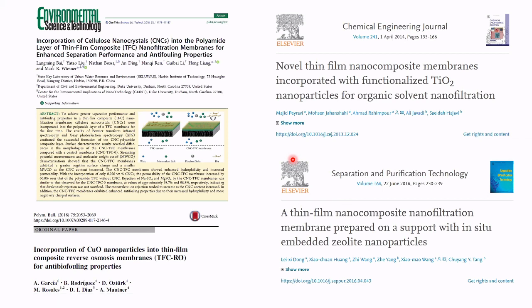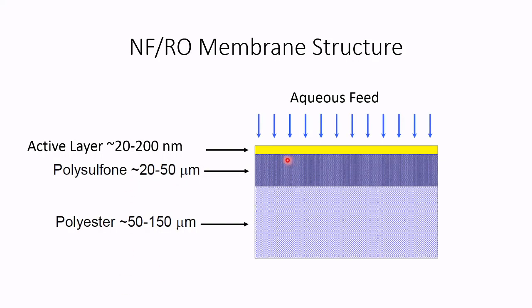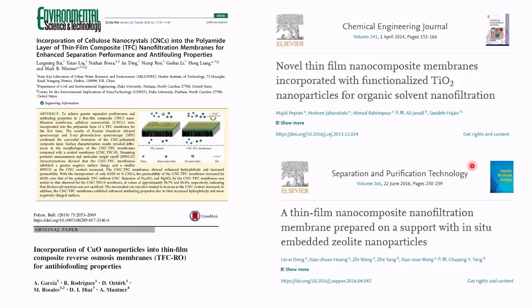So here we see, just to recall the structure of a membrane, the active layer is that top layer. So what these papers are really doing is embedding nanoparticles within that top layer and then assessing how that impacts rejection. Interestingly, you see another here, incorporating nanoparticles into thin film reverse osmosis membranes for anti-biofouling properties. So these nanoparticles are able to, for instance, contribute to reducing biofouling, reducing the amount of microbial accumulation on the membrane. So not only changing membrane properties in terms of what they can reject, but also changing membrane properties in terms of how susceptible they are to some of these problems like fouling.